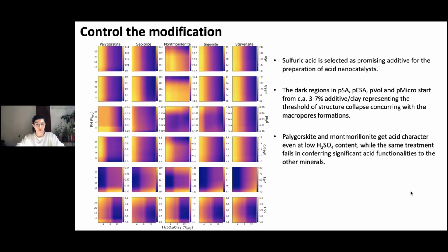reducing the descriptor space. The yellow regions are the improvement areas of the properties, while the dark regions represent a deterioration of the properties. So the dark regions represent the threshold of the structure collapse, concurring with micropore formation. Palygorskite and montmorillonite, for example, gain acid character even at low sulfuric acid content, while the same treatment fails in conferring significant acid functionalities to the other minerals. And sulfuric acid was selected as a promising additive for the preparation of nanocatalysts.